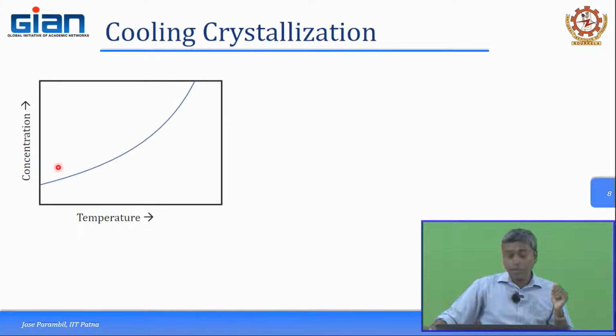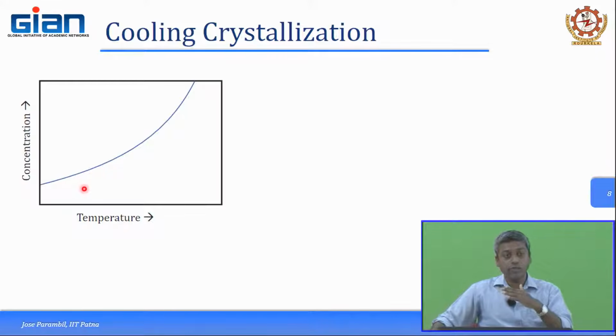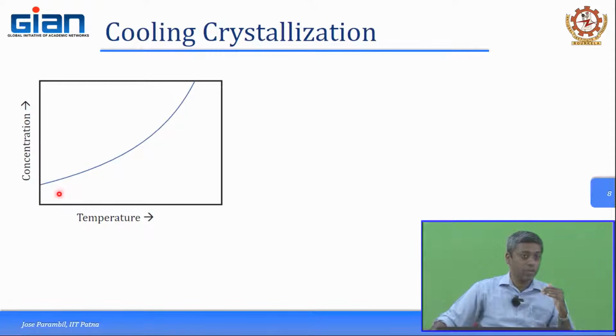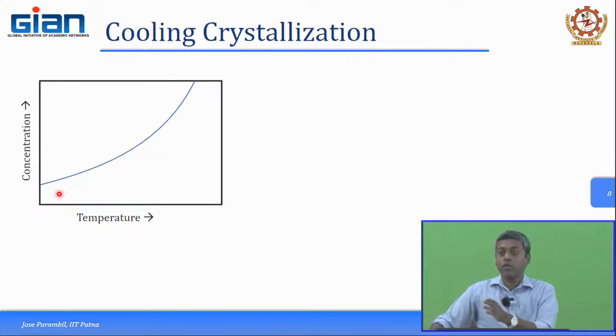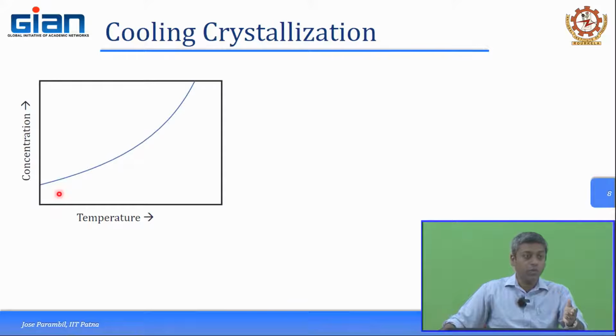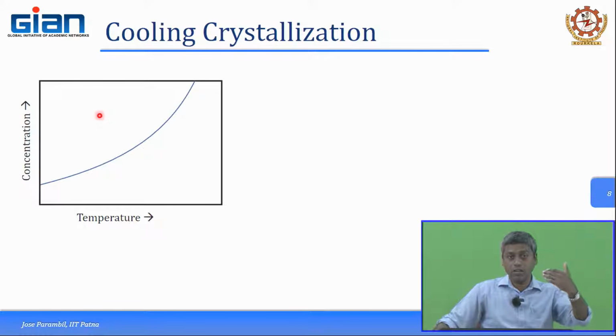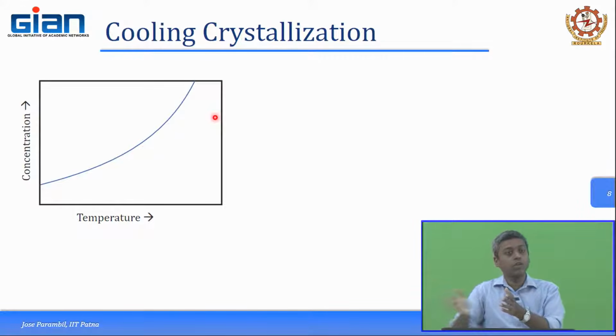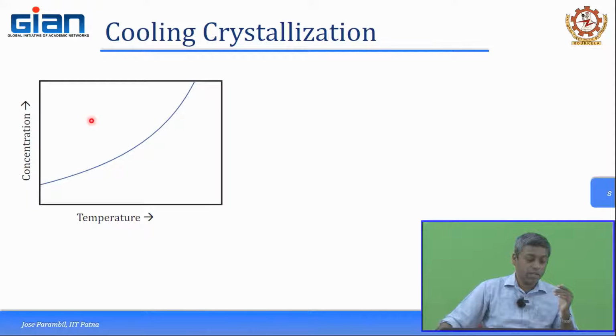Now, going back to your questions in the sense of how the solubility. So, if you have a material which has got a very highly sensitive curve, so a steep curve over here where the solubility is highly dependent on the temperature, it would be very good for you as far as the cooling crystallization is concerned, because you will get a much higher yield out from it by decreasing from, let us say, T1 to T2, and that for a given delta T, your slope of the curve would be much higher, which means that you would get a much higher yield of your material. So, that is one way of producing crystals.